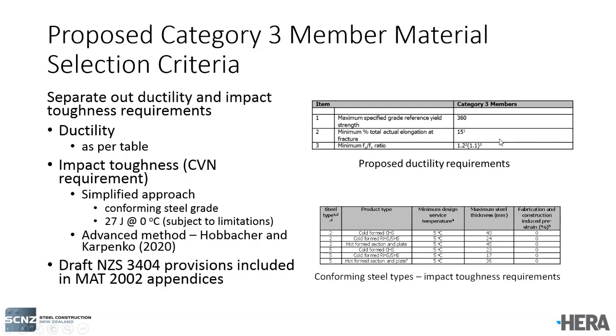We have a bracketed value of 1.1, and that's saying if you determine the FU over FY ratio from the actual data on a test certificate, so if you pull off the yield and the ultimate tensile strength off a test certificate and compute that number, you can have a slightly reduced value of 1.1. There's also the impact toughness requirements. We have two approaches. One is what we call a simplified approach, and this is pretty much the same as NZS 3404 Part 1 2009, or very similar. There's a requirement for 27 joules at 0, but it is subject to some limitations.